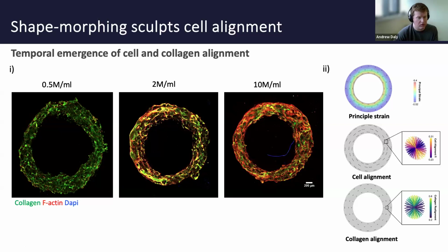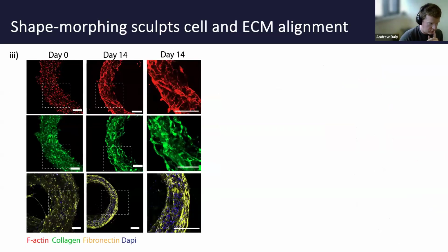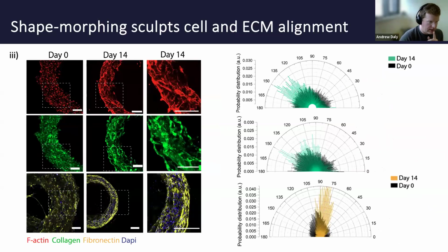The model was also able to predict this. So the principal strains that were developing in the tissue, or the direction of maximum stretch, cells were aligning in that direction. We were able to predict that with the model system, and we were also able to mirror similar changes in the extracellular matrix orientation. This is just looking a little bit closer and quantifying it. So here at the start, we don't see too much organization just after printing, but over time we start to see more of it emerging in this particular direction along the principal axis.